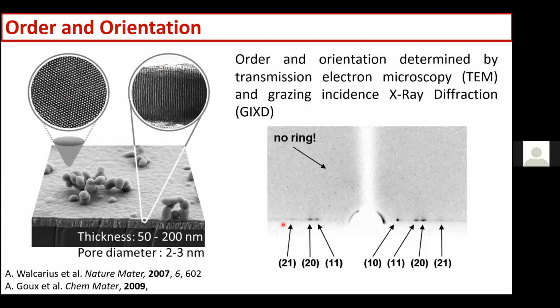Another characterization technique is GIXD, where we could verify that we had a long distance order of the film, so we maintain this arrangement over a large surface area. And here, if we were seeing rings, it would mean that we had many silica beads on top of the surface. But here, with the correct conditions, we manage to control the film formation without the appearance of these rings, and so it shows that the deposit is only the film and not beads on top.